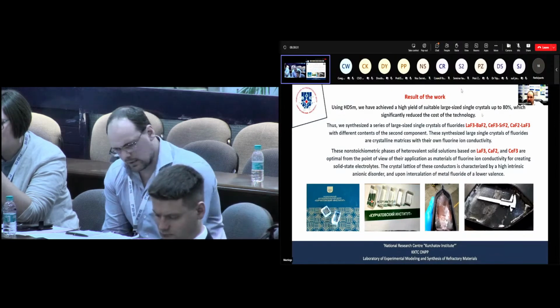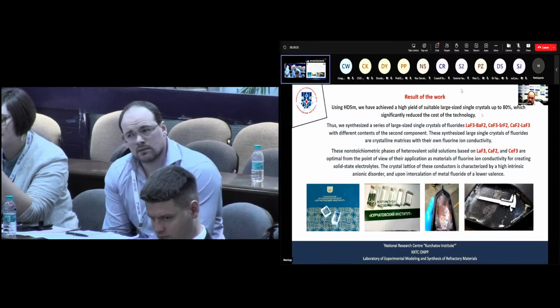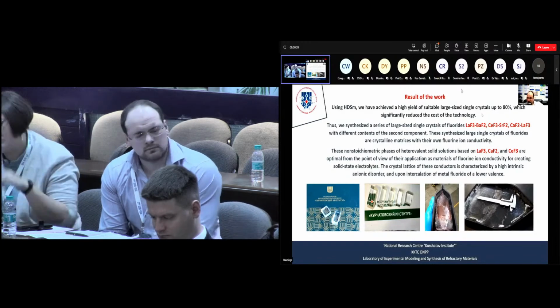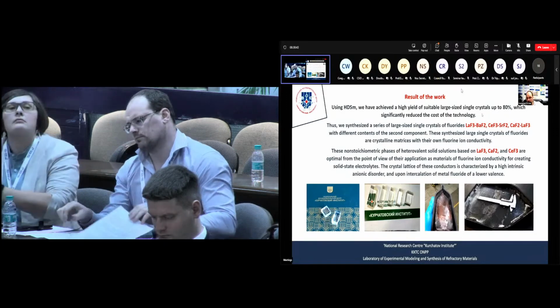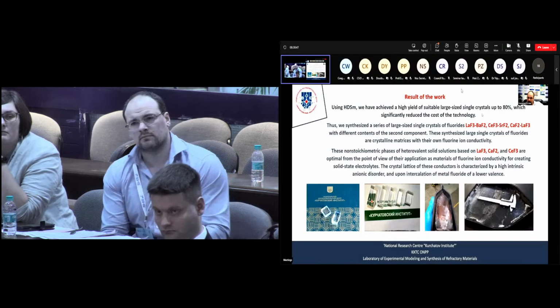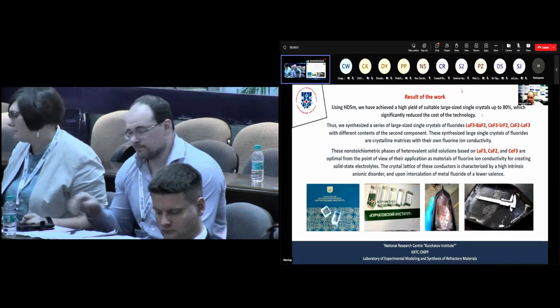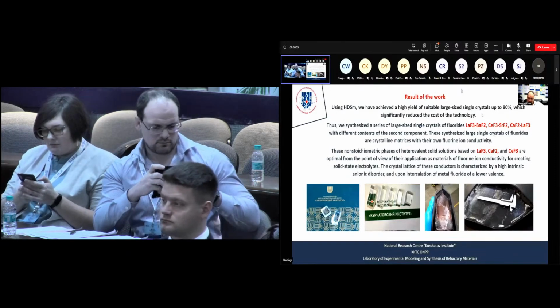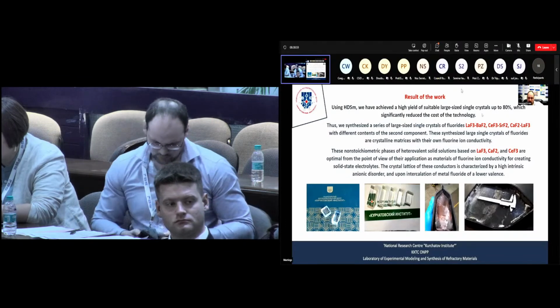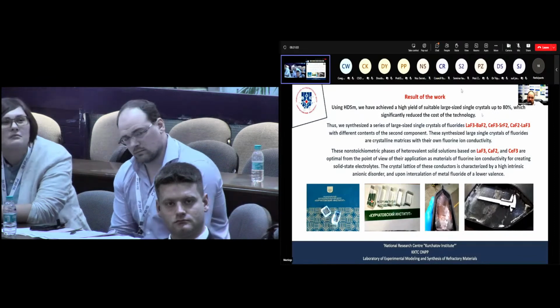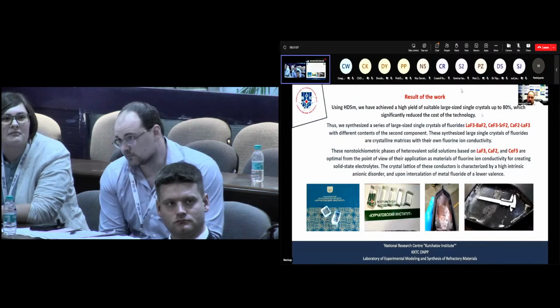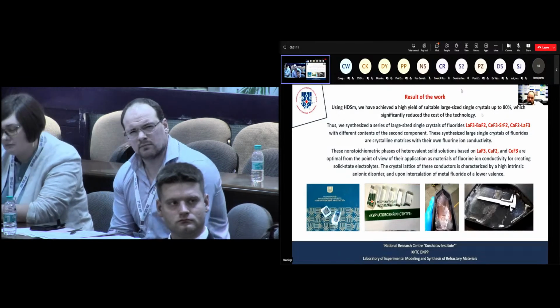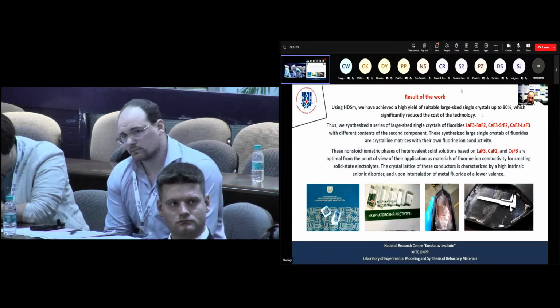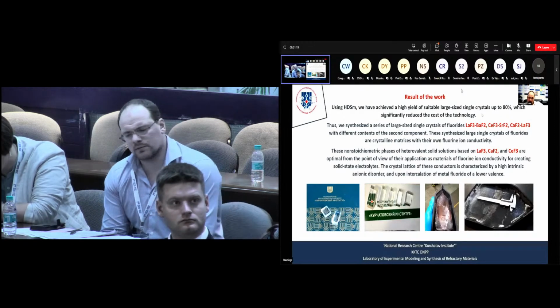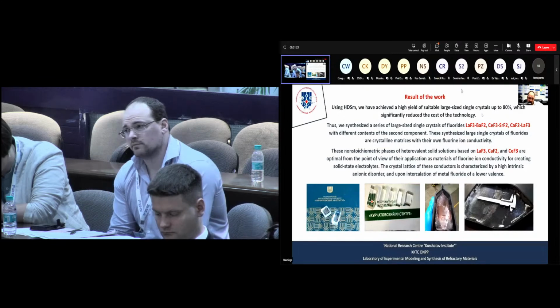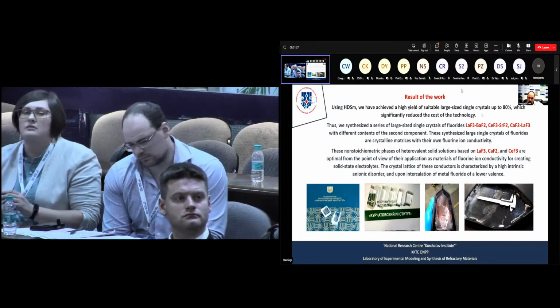Thus, we synthesized a series of large-sized single crystals of fluorides: lanthanum barium fluoride solid solution crystals, cerium strontium fluoride solid solution crystals, and calcium lanthanum fluoride solid solution crystals, with different contents of the second component. These synthesized large single crystals of fluorides are crystalline matrices with their own fluoride ion conductivity. These non-stoichiometric phases of heterovalent solid solutions based on lanthanum, calcium, and cerium fluoride are optimal from the point of view of their application as materials with fluoride ion conductivity for creating solid-state electrolytes. The crystal lattice of these conductors is characterized by high intrinsic anion disorder, and upon intercalation of metal fluoride of a lower valence.